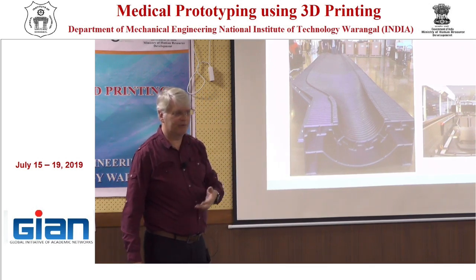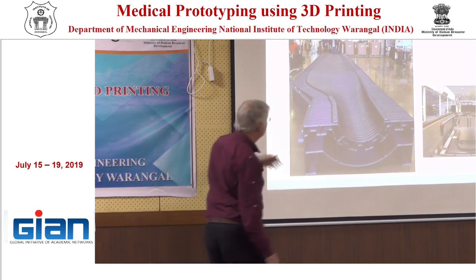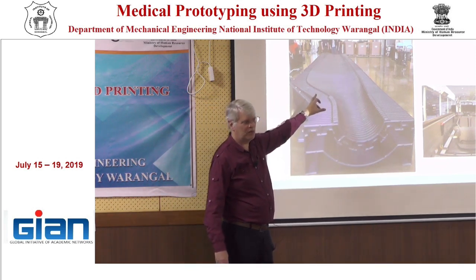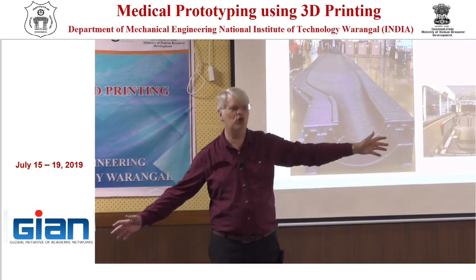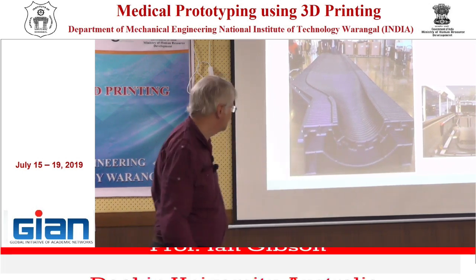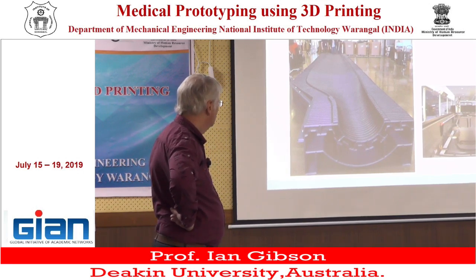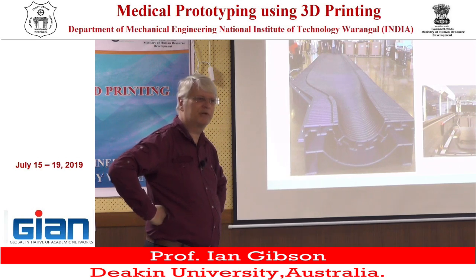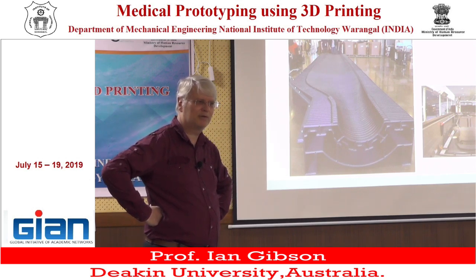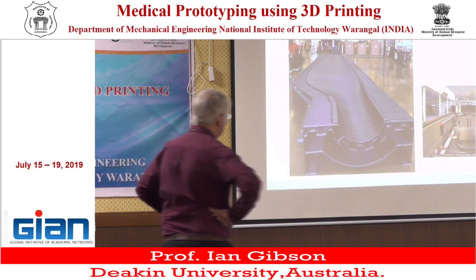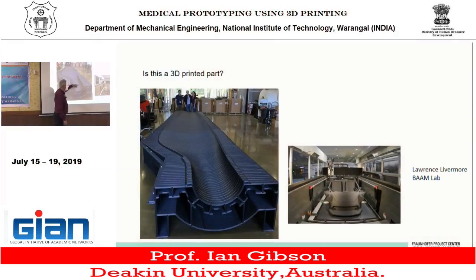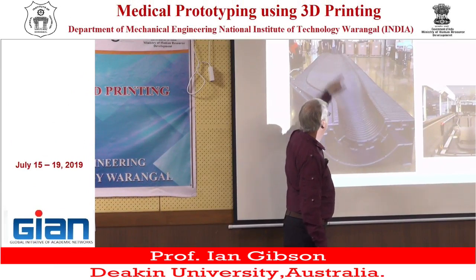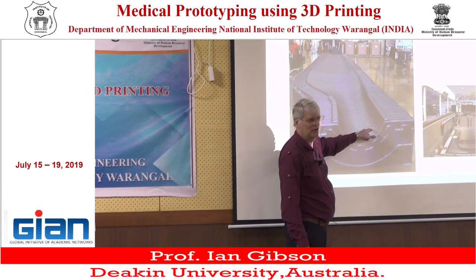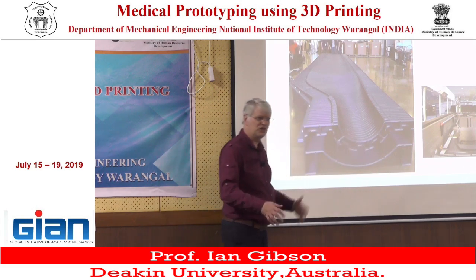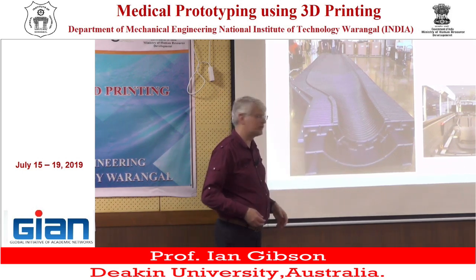They make them using carbon composites. And this can be, for some windmills, 30 meters long. Some of these windmills are huge, absolutely huge, scary things. If you're using composites, carbon composite manufacture, it's an exothermic reaction, yes? Exothermic process. So if you've got a tool this long, you start putting your carbon layups here. By the time you get to here, there's all sorts of distortion going on here because of the reaction. So you need to control the heating and cooling processes.